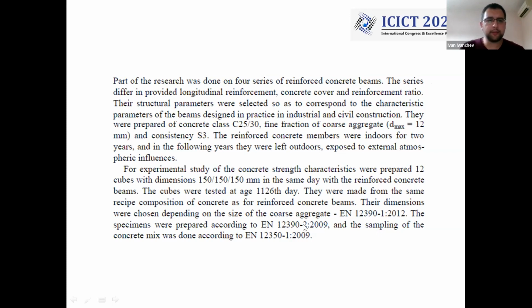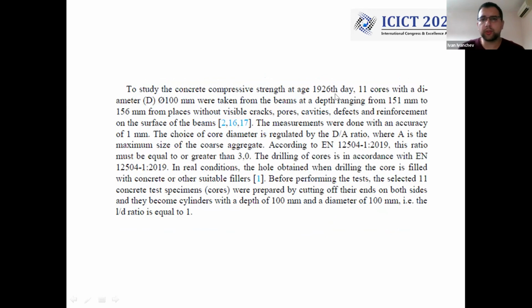They were cast on the same day as the beams, and the tests on the cubes are made on the 1126th day. All the measurements are performed according to the European standards EN 12390 part 1, part 2, and EN 12350-1. About the cores, they were drilled at age 1926 days, with a diameter of 100 millimeters and depth ranging from 151 to 156 millimeters, from places without visible cavities, cracks, pores, defects, reinforcement, etc.